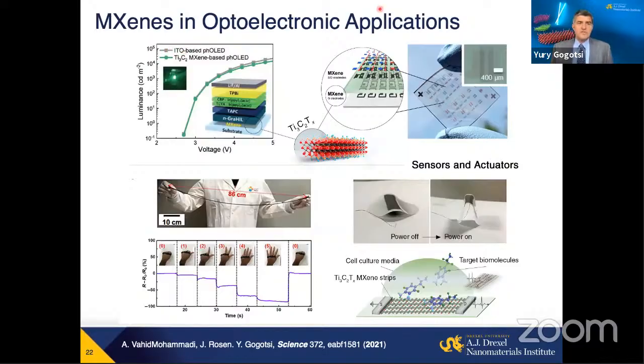I already showed you, for example, a variety of optical properties combined with conductivity going to 10-20,000 Siemens per centimeter. And one obvious application for a two-dimensional material here is in transparent electronics, for example, replacing indium tin oxide in organic light-emitting diodes, OLEDs. You can see that the performance shown here for a Ti3C2Tx MXene film and ITO is largely analogous. This is work with Korean collaborators.